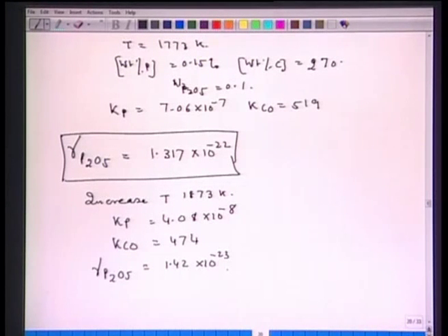That is, if you go for a little higher temperature, the phosphorus reaction may occur, but then you still require a very large reduction in the value of gamma P2O5. Therefore, for the simultaneous removal of carbon and phosphorus, one has to see that a slag which has a very low value of gamma P2O5 is formed, and then carbon and phosphorus reactions may be allowed to take place simultaneously such that the carbon removal is slightly delayed as compared to the phosphorus removal. So, that point you should remember. I will be needing it when we go into the modern steel making practice.